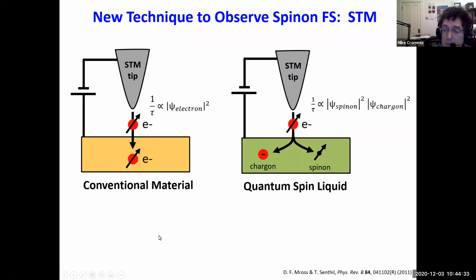But if I have a quantum spin liquid, things are different because now if I try to tunnel an electron into the quantum spin liquid, it has to break up into a chargon and a spinon. And so now the rate at which the electrons tunnel in is going to be proportional to the product of these two different particles' wave functions. And so the rate at which the electrons tunnel is going to be proportional to the product of the spinon wave function times the chargon wave function squared. Because these two things have to happen at the same time, so the probability is going to be the product.